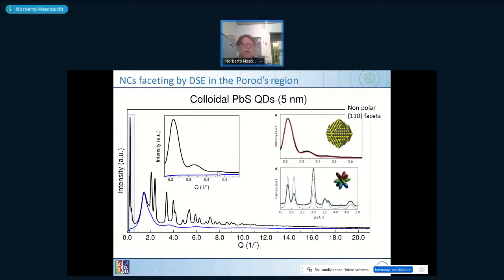These are the so-called Porod regime of small angle scattering, measured with wide angle scattering techniques and simulated by the same Debye model we use for everything else. So the Debye scattering equation is also able to account for the small angle scattering, which is normally treated with a completely different approach. Here you have a matching, and the matching was only possible by taking this kind of shape.